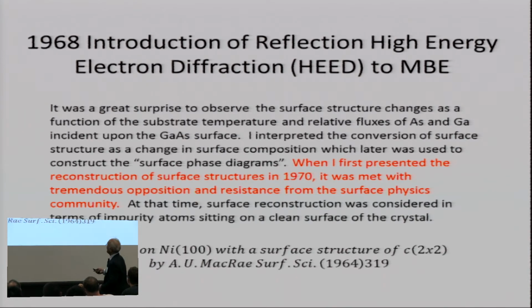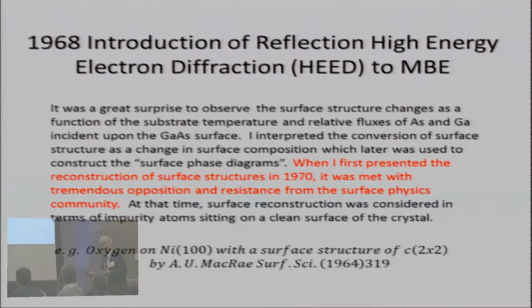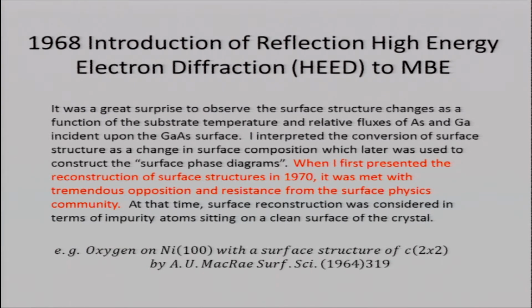But you see, this gun gave me a really important route to how to grow films. It was a great surprise to observe the surface structure change as a function of substrate temperature and the relative fluxes of arsenic and gallium incident on the gallium arsenide surface. I interpreted the conversion of surface structures as due to surface composition changes. Later I used those surface composition changes to plot the surface phase diagram.